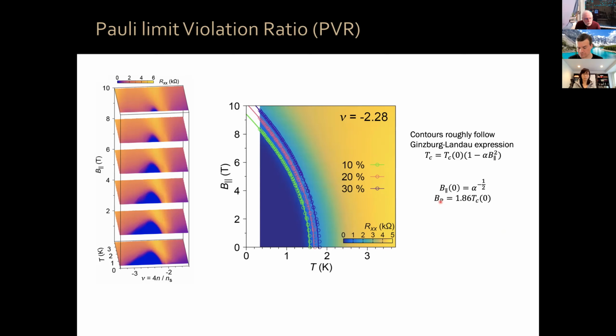And if you calculate what's the Pauli limit for each of these thresholds, they have corresponding Pauli limits, okay? Which are here. As you can see, superconductivity survives up to much, much higher fields than the Pauli limit. In fact, at this filling factor, the Pauli violation ratio is over a factor of 3, okay?